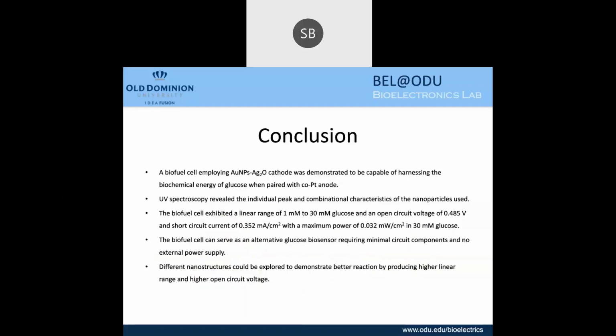So our conclusion is that we were able to make a biofuel cell combining two nanoparticle structures. We did an analysis using UV spectroscopy and cyclic voltammetry, and also we got a linear range of 1 to 30 millimolar of glucose.